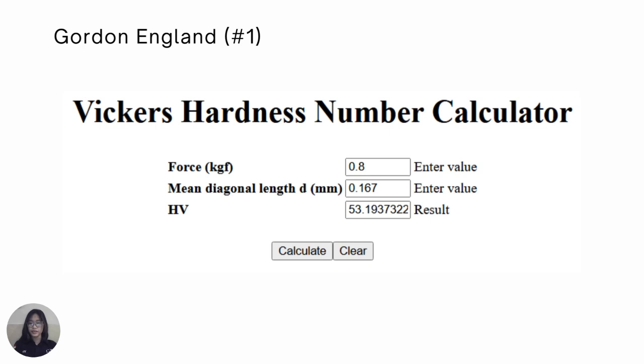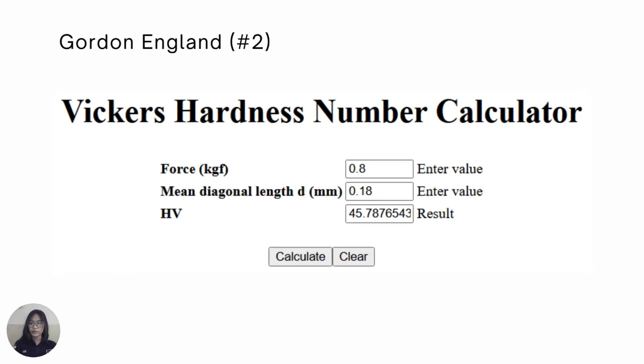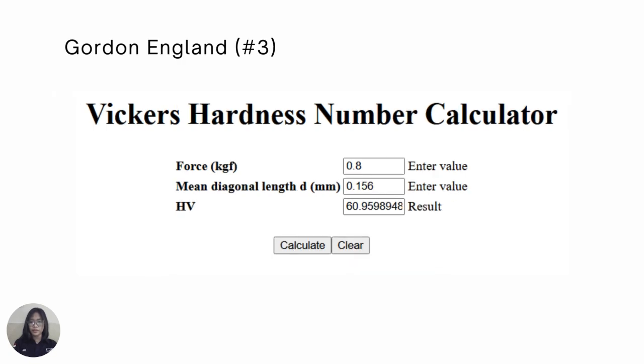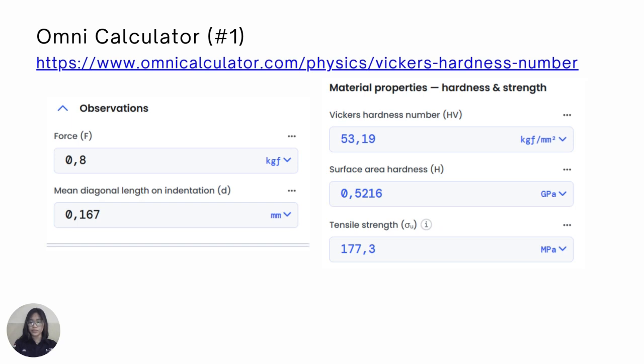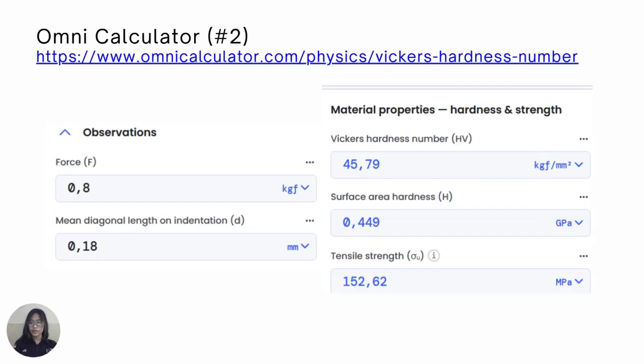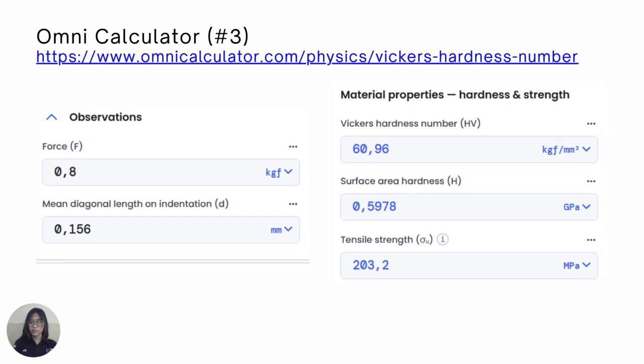Okay, so this is the Vickers hardness number and result for the first indentation using Gordon England. This is for the second indentation, which has the mean diagonal of 0.18. And this is the third one, still from Gordon England. Moving on, we tried Omni Calculator. The only difference here is that it tells the surface hardness and the tensile strength, but the Vickers number still remains the same. For the first one, it is 53.19. The second is 45.79. And then the third is 60.96 or 61.